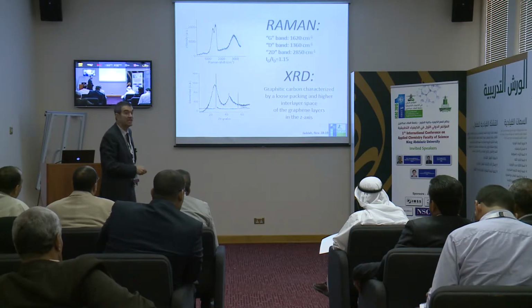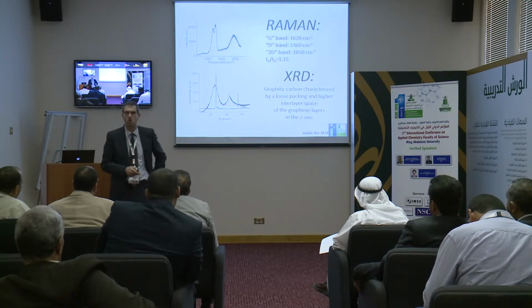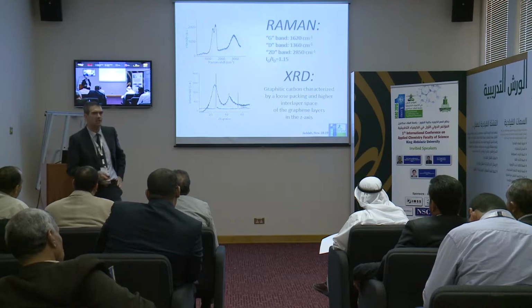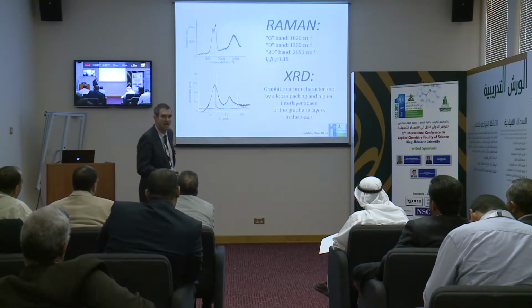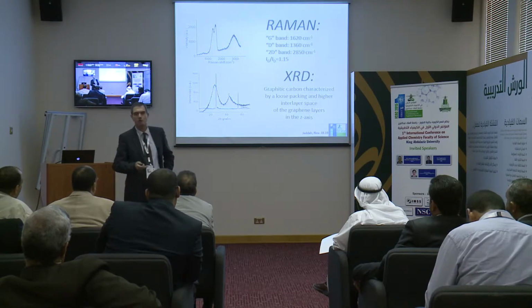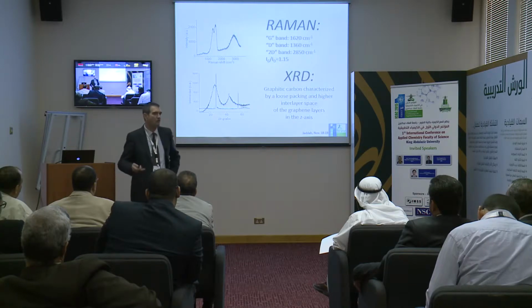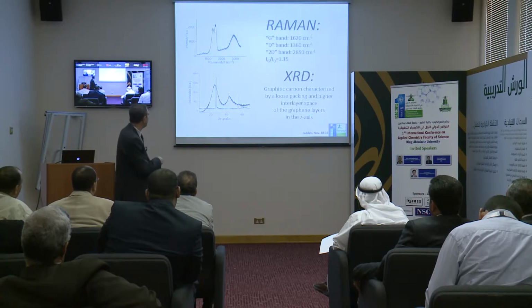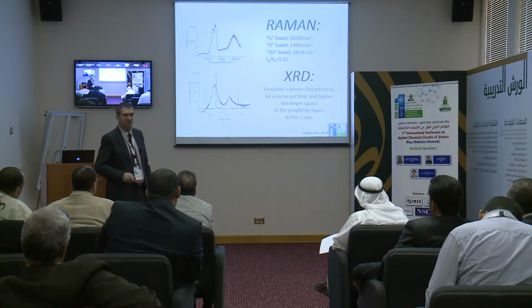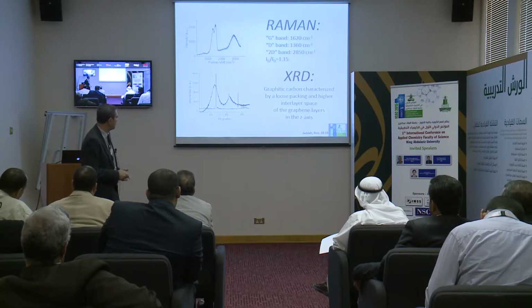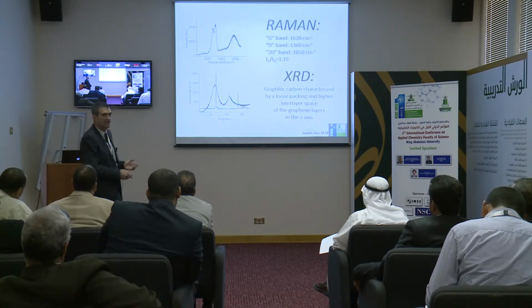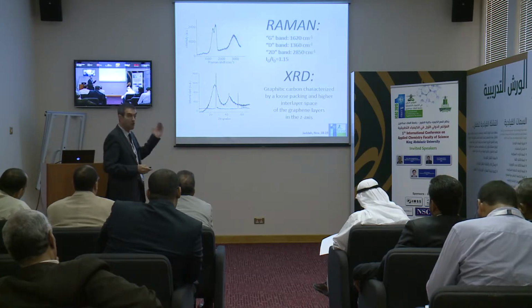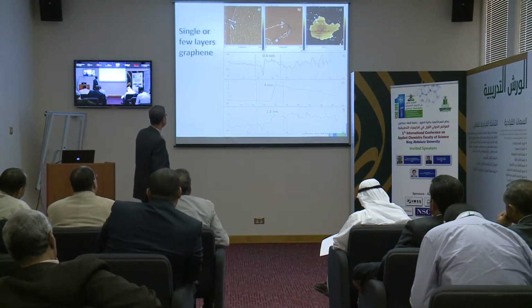So for instance, here the yield of exfoliation is almost complete in some of the materials. This means that if we have 1 gram of this carbon residue and we sonicate, we have 1 gram of graphene. So the yield of this is very high, and this contrasts with the difficulty of graphite exfoliation. And the XRD clearly provides a nice example of why. What is the reason for this?